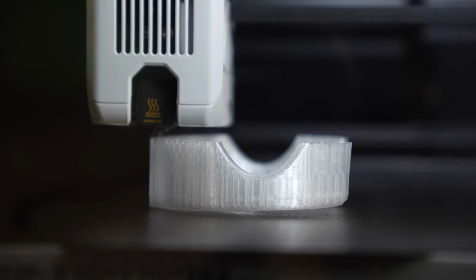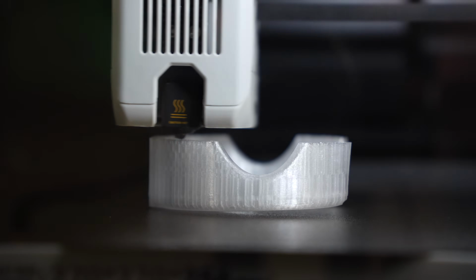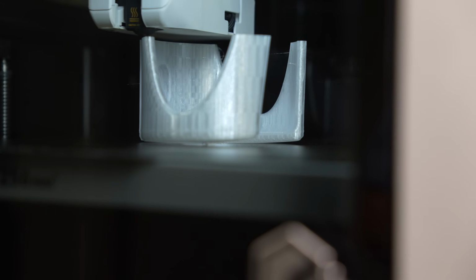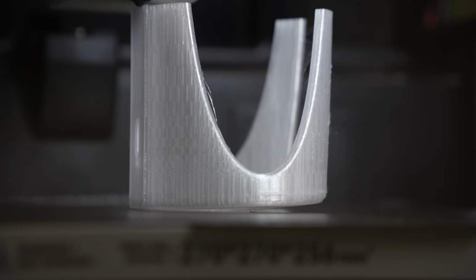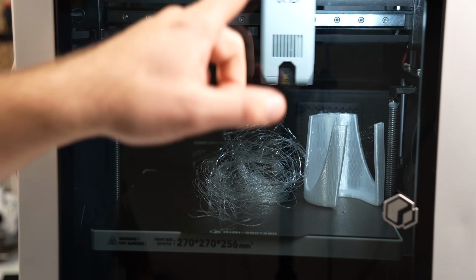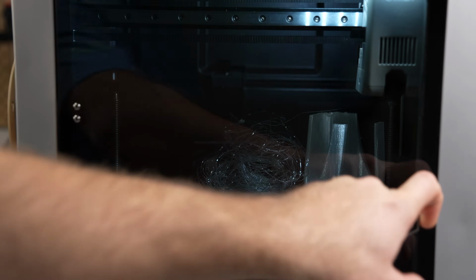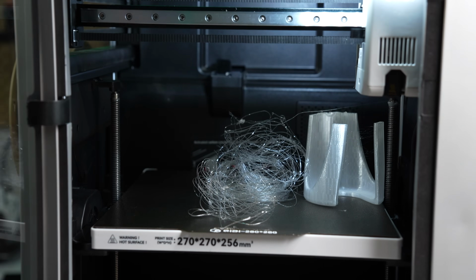For the side without, it started warping pretty quickly, and at about the halfway point, I was really impressed that it was actually still holding on to the build plate. Well, I probably should have stopped the print there, because when I came back 15 minutes later, the hot end was just air printing and the part had shifted off of the build plate.